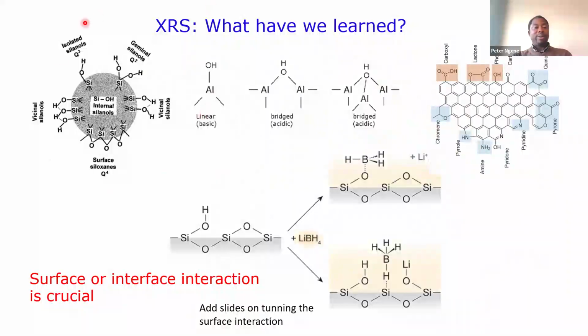And why is it? Because if you take silica, for example, we do know that silica has a lot of surface groups, different kinds of OH groups on the surface. Some are basic, some are acidic, especially for alumina. In terms of silica, it's only really basic. And in terms of alumina, we can have acidic groups and basic groups. But alumina is also quite different because you can even have Lewis acidity. I think that's the point I'm trying to make. You can have Lewis acidity on that.